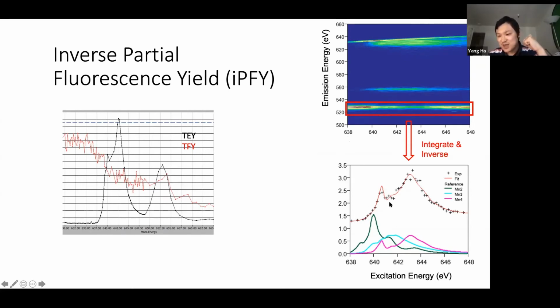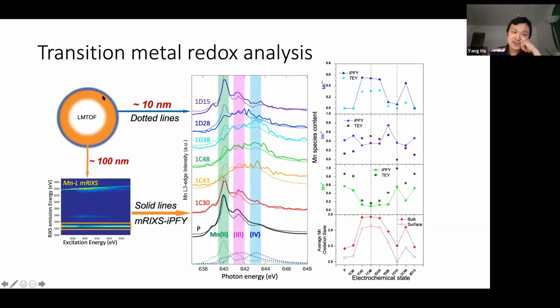And then with this manganese L-edge, we can fit it with the standard spectrum, and then we can end up with the amount of each composition in the samples. So this is our normal working protocol. So for the samples we have, we can measure the total electron yield from our TEY channel for each sample we have. So we can have the L-edge for the surface. And depending on what element we have, we can either measure the total fluorescence yield directly, or we can measure the transition metal L-edge and use the iPFY to obtain the non-distorted L-edge for the bulk.